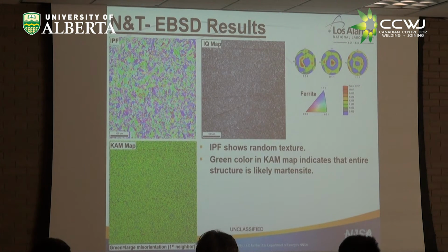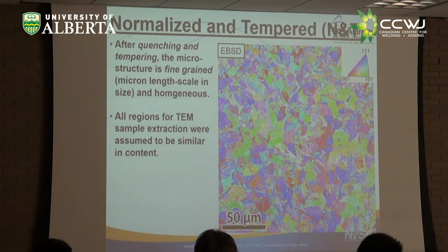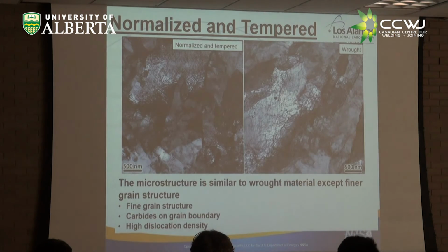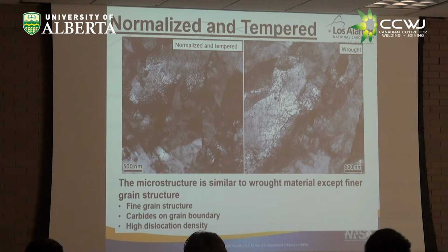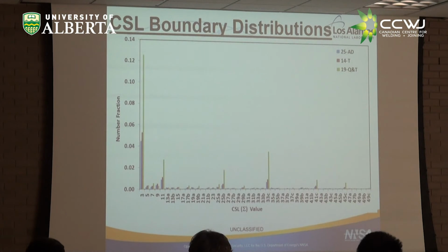The electron backscatter diffraction results are exactly what you think it should be. You have all green in the Kernel Average Misorientation (KAM) map, indicating that it's likely martensite. So everything here is pretty much as we would have expected, and completely different than what we saw in the as deposited microstructure. And then also here is some more EBSD data. Basically, it looks just like the wrought material. Okay, here's some of the TEM stuff again. High dislocation density, fine grains, carbides on the grain boundaries. And this looks much like the wrought material, which I won't show you.